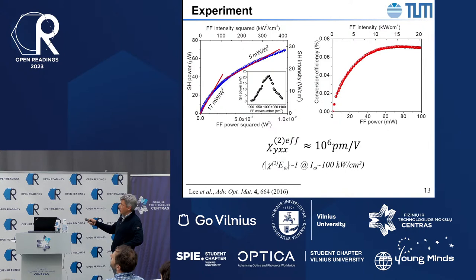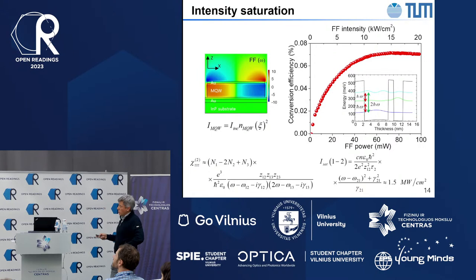And this is how the conversion efficiency changes as we increase the laser power. So you can see immediately here that we have a little bit of trouble. Yes, the nonlinearity is huge, so for low intensities, everything looks great. We have an incredible slope of 17 milliwatts of second harmonic generation per watt squared. But at high intensities, we move a bit into saturation. And that right now is the problem that limits us. And we can understand why this is happening.